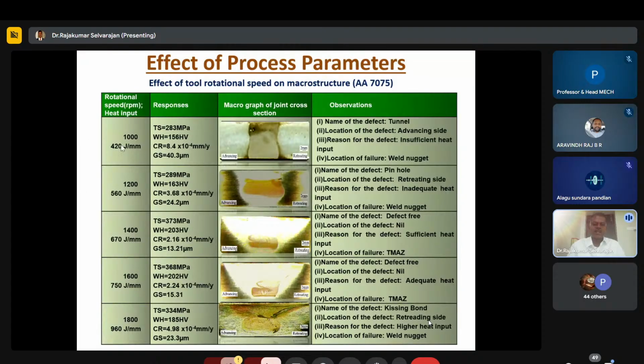Next we conduct 1200 RPM. You can see the pinhole defect on the retreating side. It is also possible due to inadequate heat input, so the pinhole defect is formed in the weld nugget. But the difference in strength is only 10 megapascal. So again we increase the rotation speed to 1400 RPM.